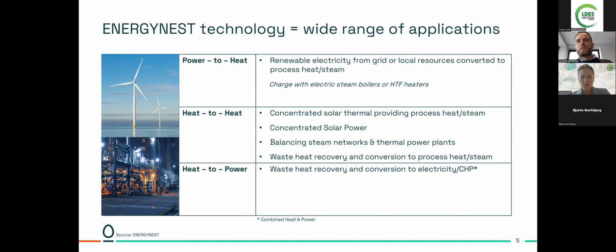And last but not least, we can also recover otherwise wasted heat from industrial processes, typically via a thermal oil heat exchanger. Then we can convert that heat into usable process heat, or typically process steam. And in the last category, heat to power, we do something very similar. We do waste heat recovery, but we can convert that heat rather into electricity, for instance, using organic Rankine cycles, either producing pure electricity or in combined heat and power mode, supplying also hot water for district heating.